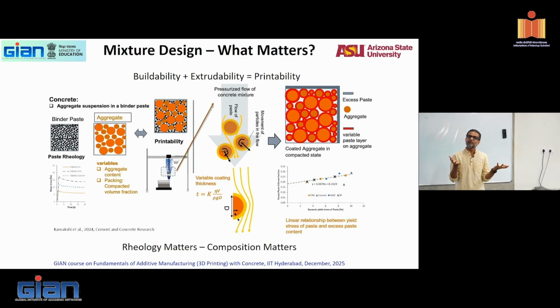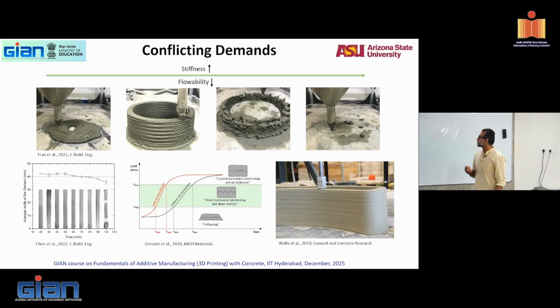So what you're doing is a paste thickness, and here is a relationship between yield stress and the excess paste volume. As the excess paste volume increases, the dynamic yield stress of the paste increases; that is an indication that you have excess paste volume. So again, mix design will also have to account for how much paste volume you have in excess of what you want to coat the surface of aggregates. Because any excess paste is a wasted opportunity, wasted resources, wasted money. So if you want mix optimization, that's what you do.